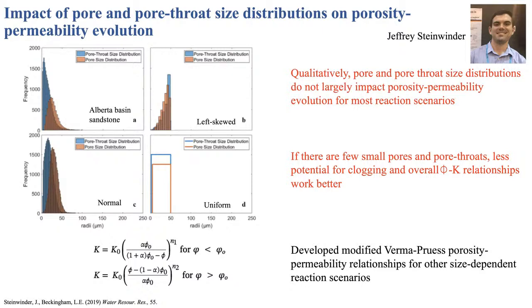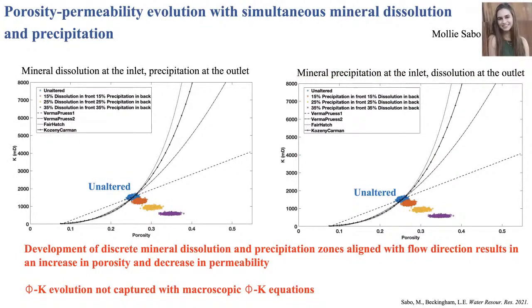This is also the work where we developed this modified Verma-Pruess equation for the size-dependent reaction scenarios. And then more recently, we've considered systems where you have simultaneous mineral dissolution and precipitation. This was done by my undergrad researcher, Molly Sabo. And so here we're having dissolution and precipitation occurring in the same network. These simulations we considered on the left here, dissolution at the inlet of the network, and then precipitation downstream towards the outlet. And what we see is that we have an increase in porosity, but a decrease in permeability, and that's not captured by the macroscopic porosity permeability equations.